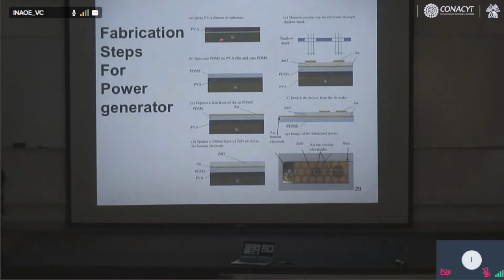So we have silicon substrate, and on the silicon substrate, you need to deposit PVA. You fabricate the sensor. All the MEMS devices start with silicon, but here silicon is only the base because your sensor is from PDMS. That is the material. You fabricate the sensor on PDMS and you stretch. This is the fabricated sensor. You stretch PDMS. It's elastic. Not too much because you break, but a little bit.